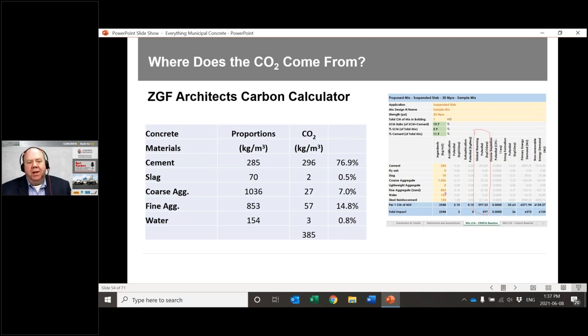So if we took an example of a hypothetical mix design that was, say, a 35 MPa C1 concrete, and we look at the mix proportions here, there's a number of calculators out there. I've used the ZGF calculator just because it does a good job of breaking out the individual components so you can see where the CO2 comes from. So for this particular mix design, the concrete's got 385 kgs of CO2. So where does it come from?